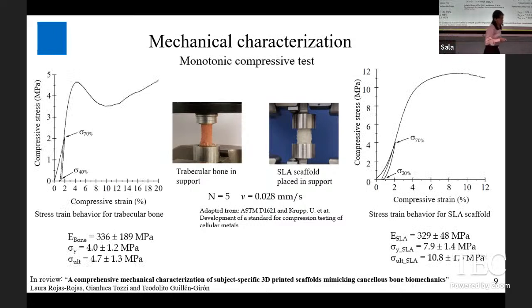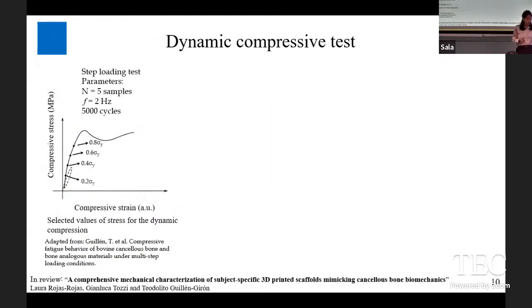When we used this procedure, we got the following result, in which we can see an elastic section for the scaffold and also an elastic section for the trabecular bone. For these two results, we obtained the elasticity and also the other two mechanical parameters, which are the yield stress and the ultimate compressive stress. The elasticity of both scaffolds are very similar, and also they are according to what we can find in literature. So also this was a very good result for us.